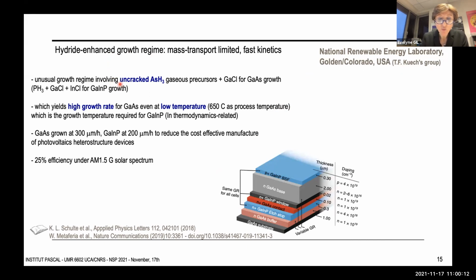It's very difficult in HVPE to prevent the cracking of arsine molecules unless you dramatically increase the flow rates in order to decrease the residence time of the molecules in the hot reactor. So a high hydrogen vector flow is used in the inlet tube of arsine together with a high global vector flow, typically 10 liters per minute. And this hydride enhanced growth regime becomes mass transport limited with very high material input flows, especially arsine. And here V/III ratios greater than 1 are used. So growth depends mainly on the partial pressure of gallium chloride.